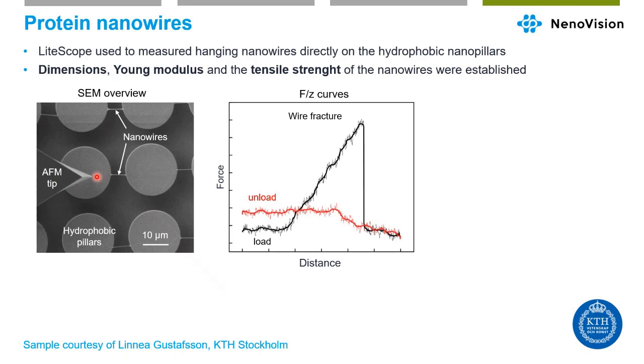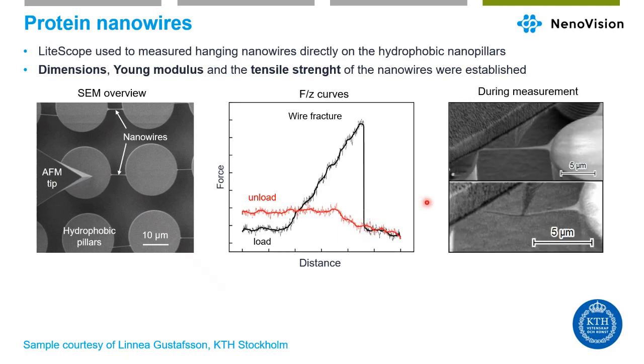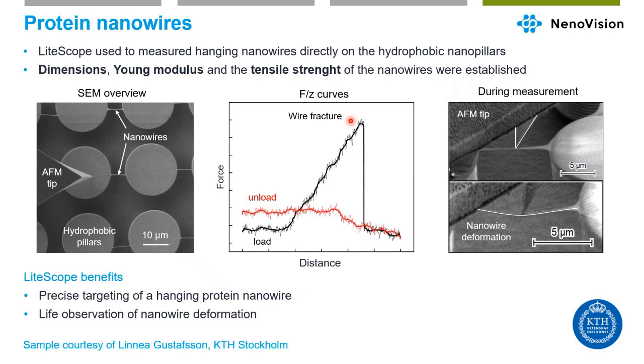So we see the probe, we see the quite big pillars compared to the nanowires, and we see the nanowires. So we used the force distance spectroscopy to find the elastic Young modulus and the strength before breaking of the nanowire. And you can see during the measurement that we were tilted in SEM, we were able to see the tip and push the nanowire to deform either elastically or plastically. So here is the breakage as the wire fractured. So with Lite Scope in SEM, we were able to precisely target the protein, and we were able to see what's going on during the measurement, during the deformation.